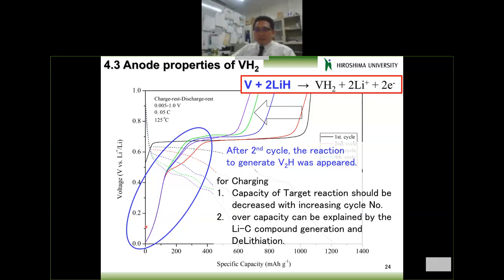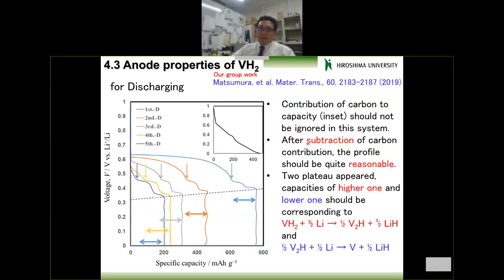So this slope phenomenon is due to the carbon black, and the other plateau phenomenon is due to the vanadium charge discharging properties. So we just assume something like this profile. This is voltage, and this is capacity.